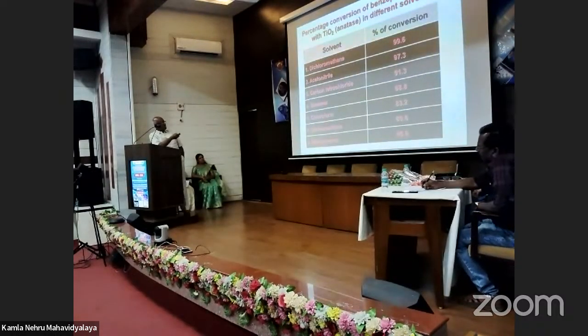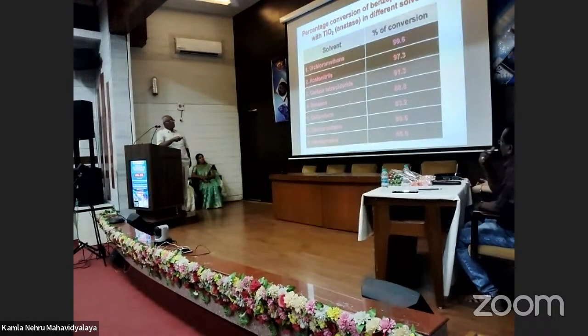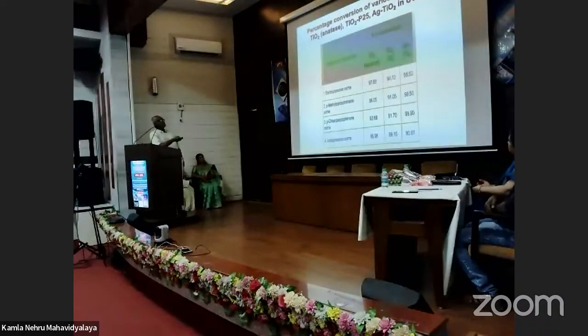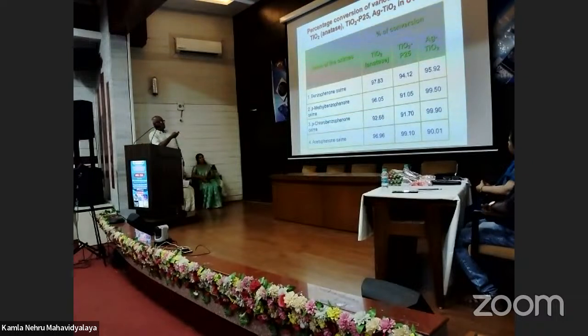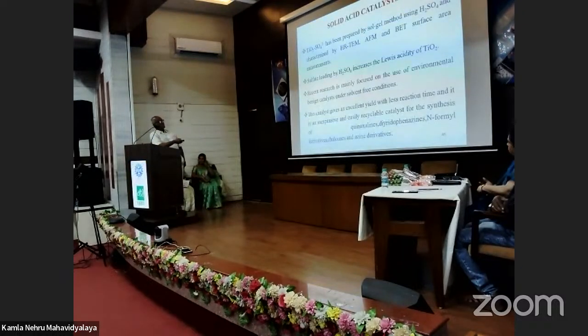Similarly, we have taken other solvents, mostly organic solvents, and among them you can see dichloromethane is the best one, and then acetate. And different oxygen sources we have taken, and the same reaction was performed with TiO2 P25, which is nothing but a mixture of two phases, rutile and anatase, 80% anatase and 20% rutile. Okay. So that's all about the work on photocatalysis.